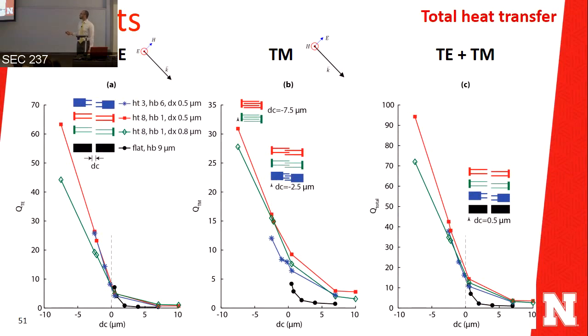In total heat transfer, all of the structured surfaces have achieved higher heat transfer than the flat one. And this total heat transfer is scaled to the heat transfer between two flat surfaces at 7 micron separation gap. You can reach up to 90 times higher heat transfer than two flat surfaces separated by 7 microns.